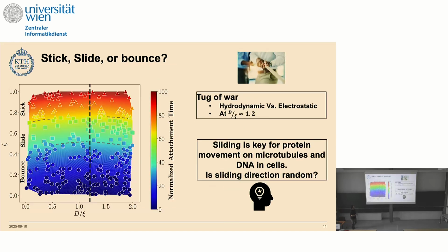In this figure, we were able to connect the size of the nanoparticle, the concentration of the polymers, and the charge ratio between the nanoparticle and biopolymers to predict the dynamics of the nanoparticle in the system. So somehow with the size, charge, and charge of biopolymers, we can predict whether this nanoparticle will diffuse into the system or stick to the fibers.